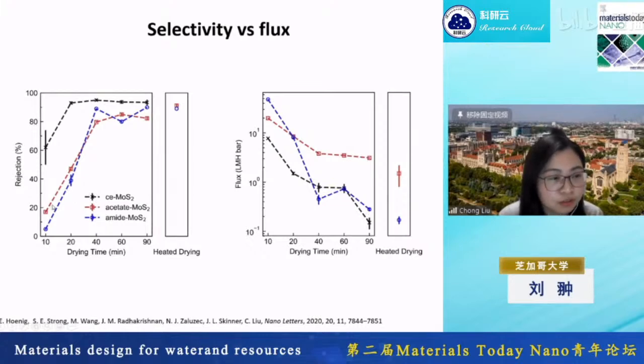But after the functionalization, we pick the acetate molecule here, which can deprotonate and carries a negative charge in water. And that membrane can easily be re-wetted and rehydrated. So as you dry up the membrane, it starts to show the 2D channel features, that it has a good selectivity to water. But at the same time, you don't lose much of the flux of water, and you see a good membrane because you see a balance of selectivity and permeability.